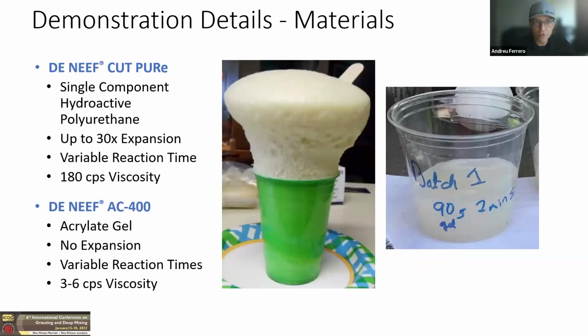So the materials we used were the NEEF Cut Pure, which is a single component hydroactive polyurethane. It expands up to 30 times its original volume. It has a variable reaction time depending on the type and amount of catalyst that you use. And it has about 180 centipoise viscosity. And that is the first picture on the left with the green cup.